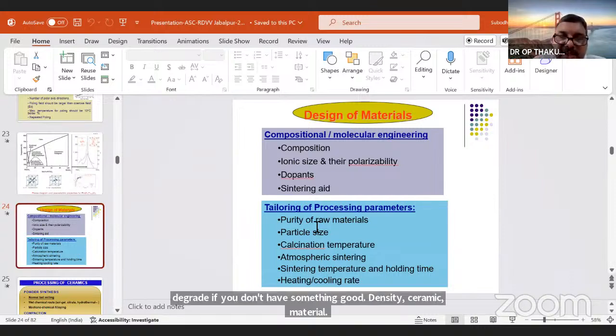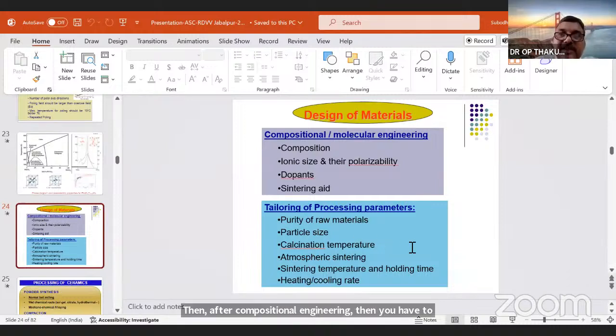After compositional engineering, you have to consider the calcination temperature, then atmospheric sintering, because most ceramics are oxides. When you heat at a very high temperature, there is a chance of loss of oxygen from your material. To compensate for that oxygen loss, you have to do atmospheric sintering or annealing in an oxygen-rich atmosphere. Sometimes people use a reducing atmosphere also, depending upon their use and application. Then the sintering temperature and holding time also play a great role, because there is solid particle diffusion, with a diffusion length, compositional gradient and temperature, which play a great role for proper diffusion between two particles.